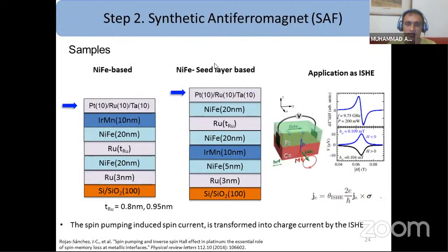Step 2, I have prepared different synthetic antiferromagnets as well, to be used for their dynamic magnetization studies, and to be used in spin valves and magnetic tunnel junctions. Here, this is a nickel iron base. I have chosen the ruthenium thickness as 0.8 and 0.95, so that there is a lot of interaction, high interaction, between the ferromagnets. Here these are ended with platinum, ruthenium, and tantalum at the top.